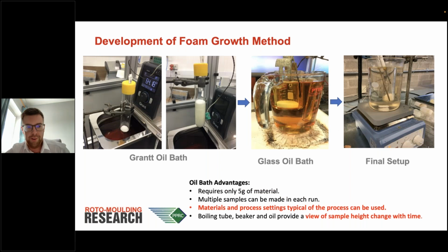So I went down the path of trying to observe this global foam behavior. And you can see the iterations that I had been through to get to my final experimental setup. We started with an oil bath, and that moved into a glass oil bath, which enabled me to image through the cross section to get the foam height change. And that then was taken a step further to a bit more of a scientific, digitally controlled setup, where I was able to maintain accurately the temperature of the oil bath.